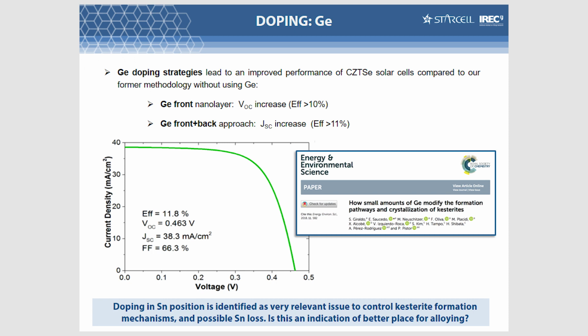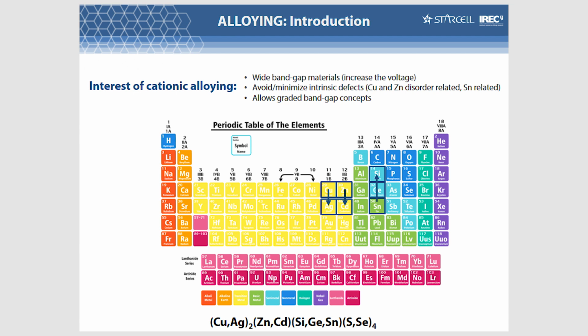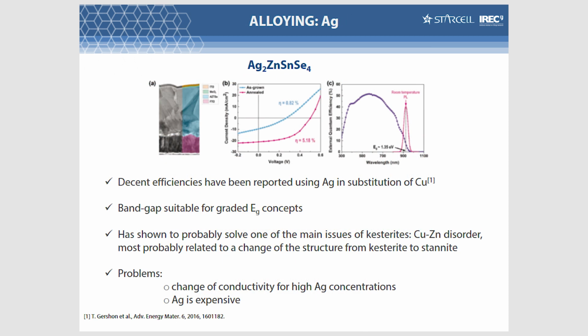Let's move to alloying. First, as Susan presents, silver can be very interesting for replacing copper, and also germanium, of course, replacing tin. Going fast about silver, ABM presented very nice results about the silver alloying compound, and what they found is that reasonably good efficiencies can be obtained with silver. But the problem is that when you start to introduce silver, you not only change the structure, you also change the conductivity type. And the silver compound is an N-type compound.